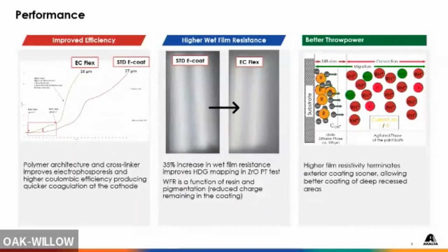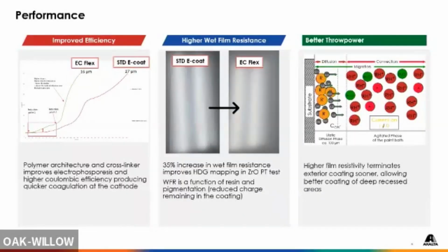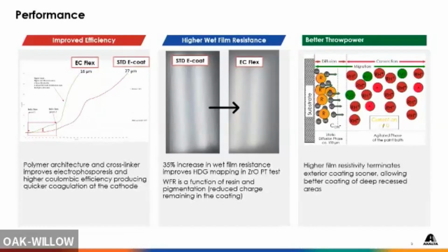As you build like that very slowly, that kills time, right? Remember, the deposition process is very finite. It's between 2 minutes and 5 minutes. So moving from the Flex to the standard, you can see I've increased my time, again, for that extra material to go ahead into those recessed areas and coat and protect some of those recessed areas.